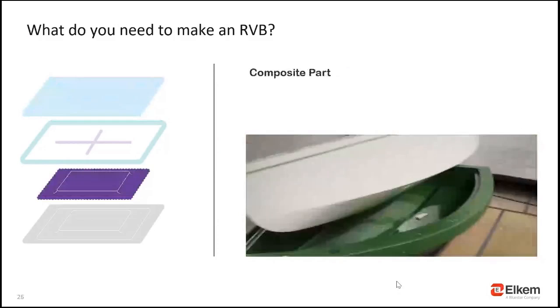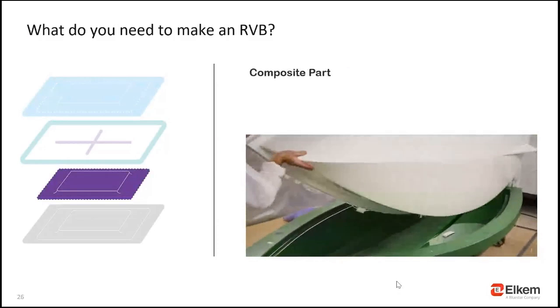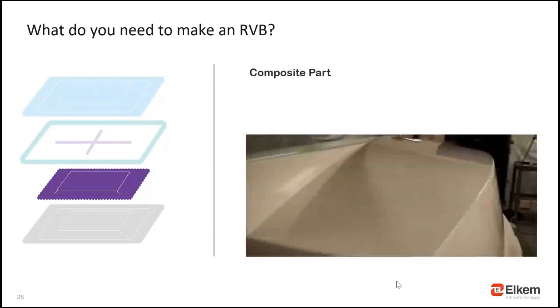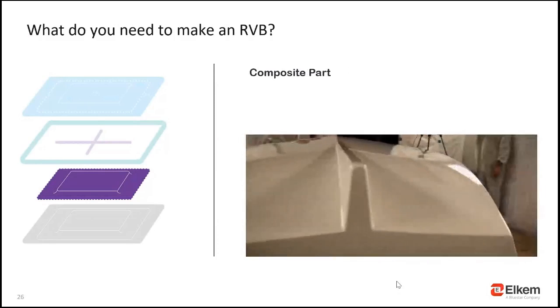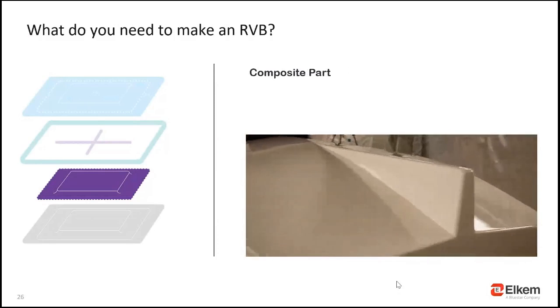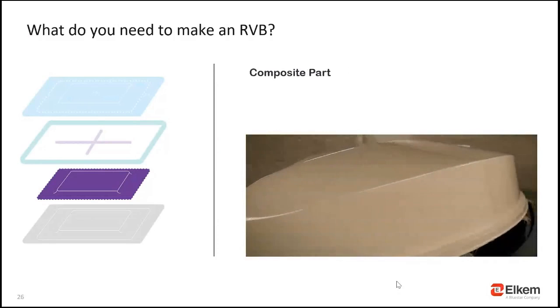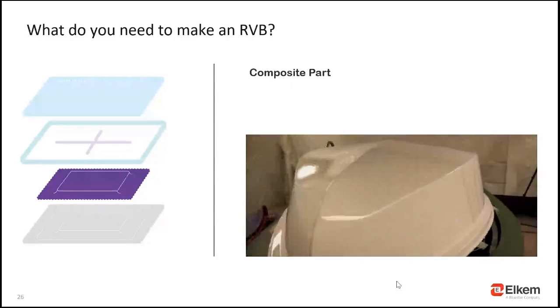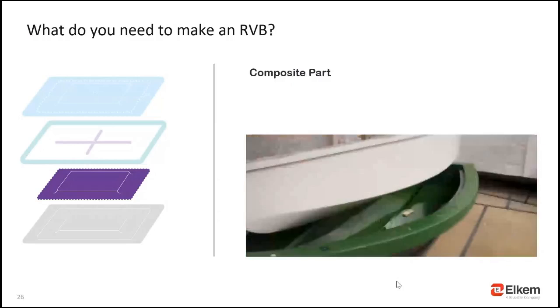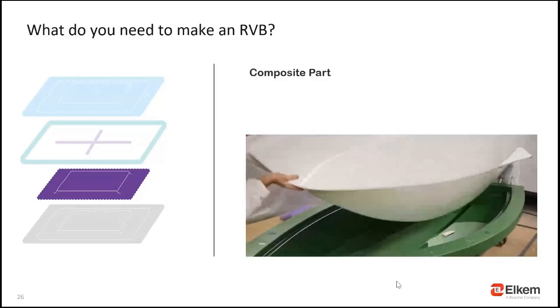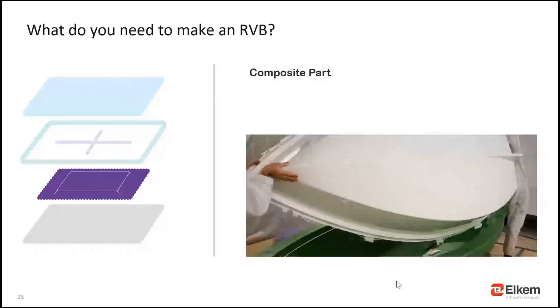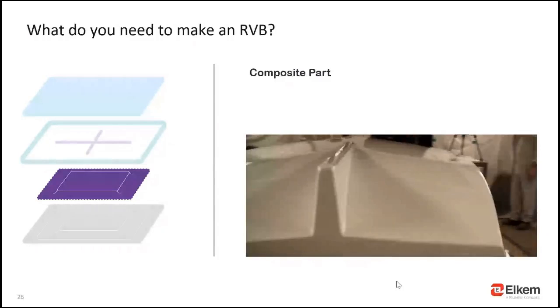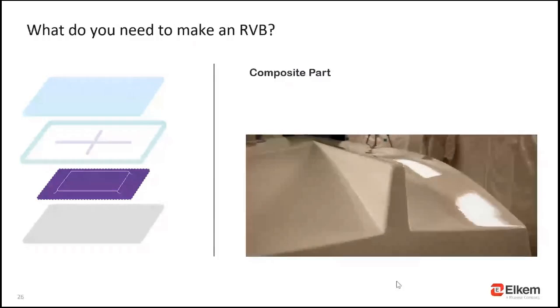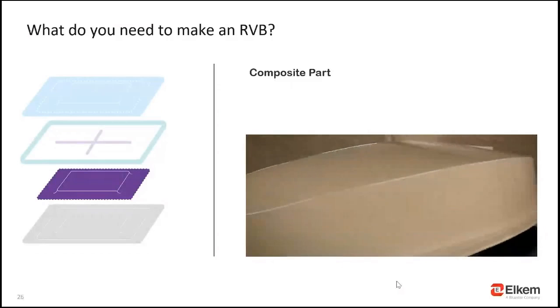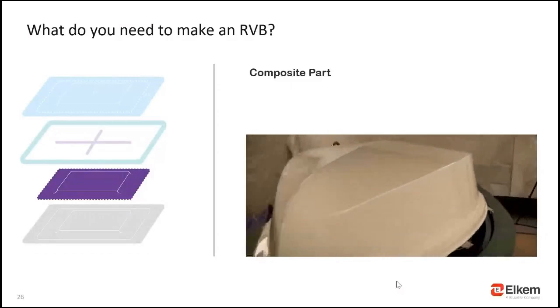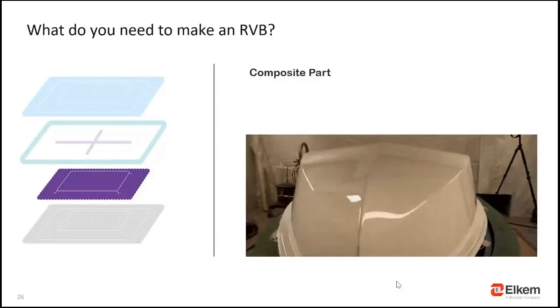Through the reproducibility capacity of silicone molds, composite parts produced by the RVB infusion process tend to have a higher fiber-resin ratio, which increases the overall mechanical properties and may reduce resin consumption. It's necessary to highlight here how no disposables related to the infusion process are necessary. The total setup time is drastically lower when compared to classical infusion. Aligned with disposables reduction, these are the main cost reduction factors.